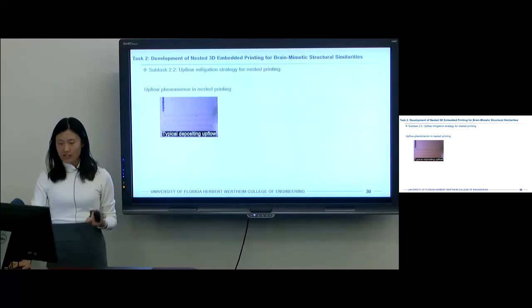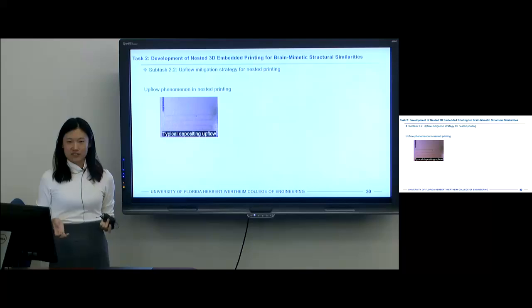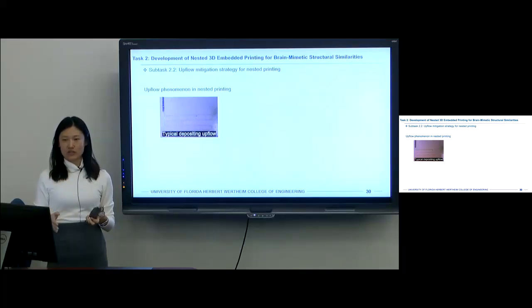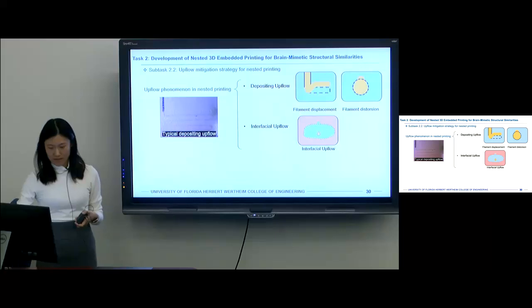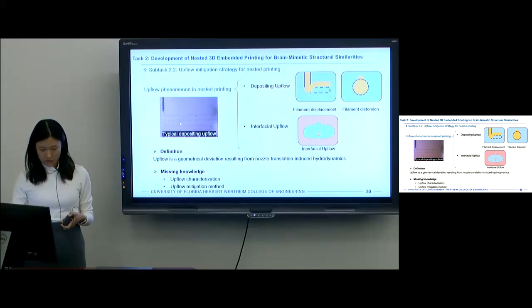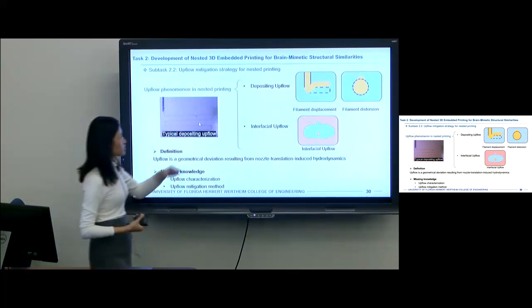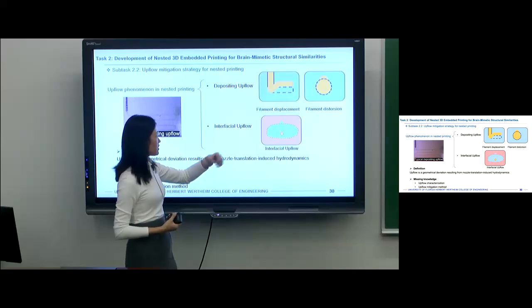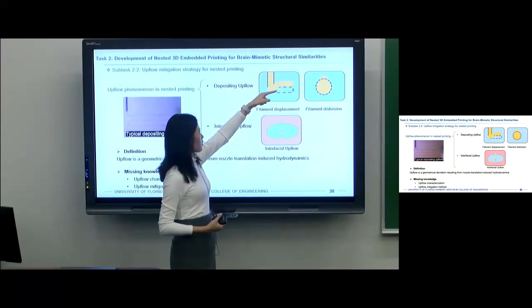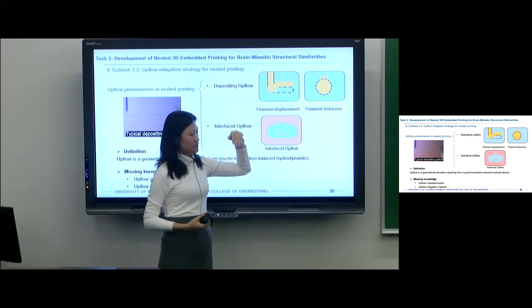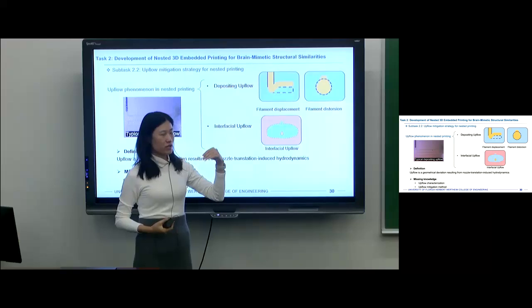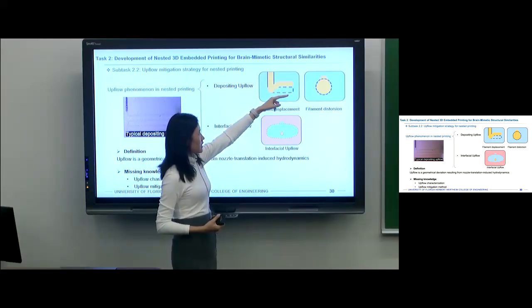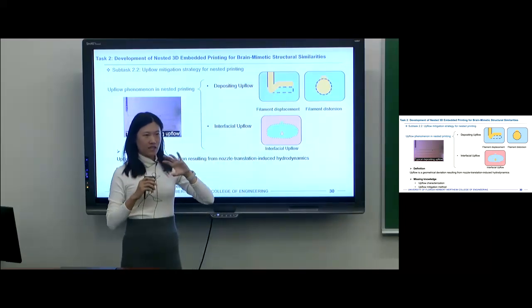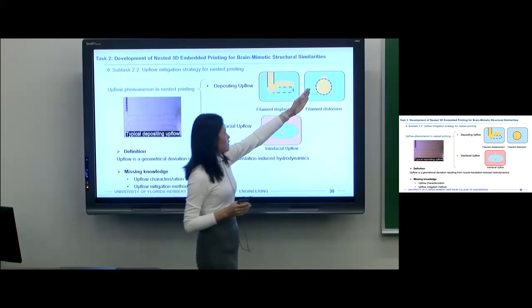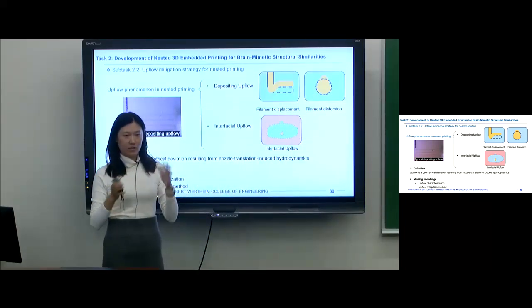However, just like a lot of other printing processes, nested printing also needs improvements in depositing fidelity. A very common phenomenon here is upflow. Upflow means when we try to deposit the material at the target position, the filaments will actually flow up a little bit. We would like this material to be deposited right here, but because of the hydrodynamics around the nozzle area, the filaments will flow up a little bit. Also, we would like to deposit the material and expect it to be perfectly spherical. However, it will be like a droplet, also due to the hydrodynamics around the nozzle region.